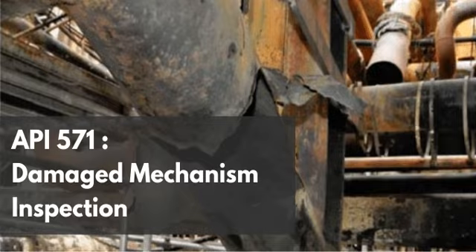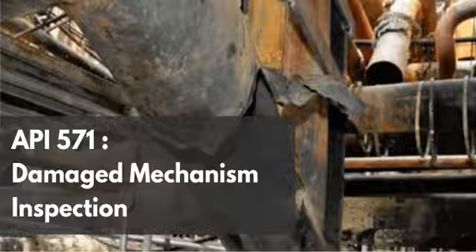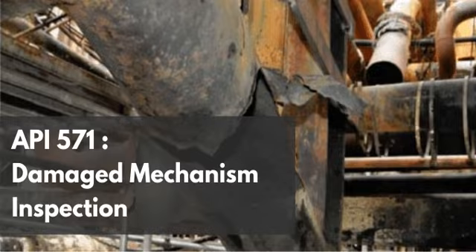Strict adherence to process temperature limits. As we discussed at length, this is the trigger. The limits exist to prevent the amine from thermally degrading into those corrosive, heat-stable salts and organic acids. If you respect the temperature limits, the amine remains a stable treatment chemical, not a solvent for your containment piping. And the third critical mitigation.